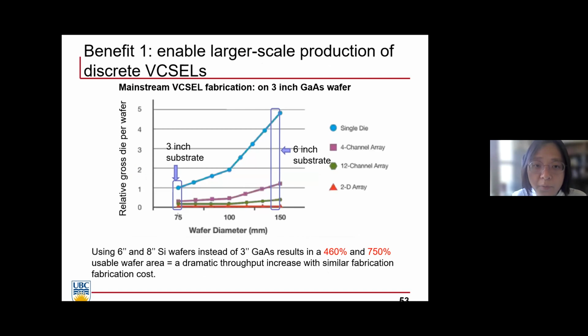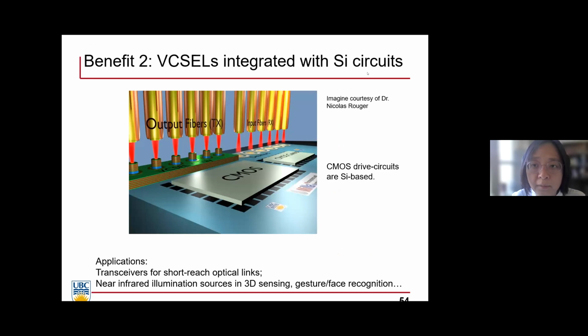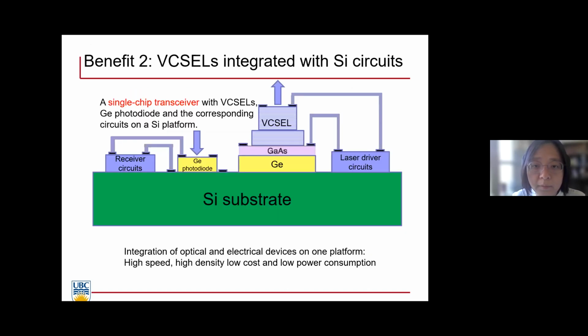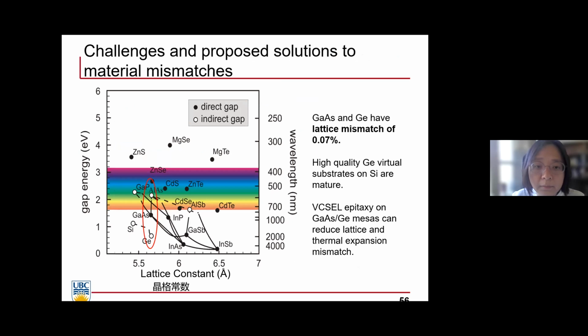So again, when we change from 3-inch gallium arsenide wafer to 6-inch silicon, or nowadays from 6-inch gallium arsenide to 8-inch silicon or 12-inch silicon, that's a lot of process area available. Also, if we use a silicon substrate, it's possible to integrate these light sources with CMOS. Yeah, VCSEL and CMOS integration. And that's really just a potential. We can have the transceiver, for example, light emitter and light detector, on the same chip, same substrate. Really the difficulty, so here we actually see germanium lattice match, but difficulties are on the thermal expansion and also on how to match the germanium lattice to the gallium arsenide lattice, anti-phase domain, for example.